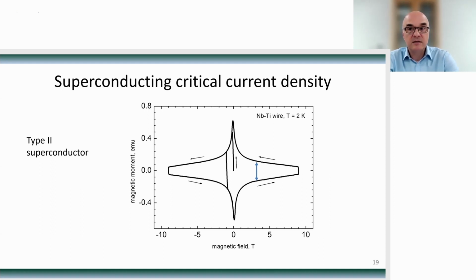And the field, of course, because there is an inductive impedance of the coil, we can produce high fields at low frequencies and smaller fields at high frequencies. But the typical figure is that at 10 hertz, we achieve a 1 millitesla field. So 10 hertz, 10 Gauss field.